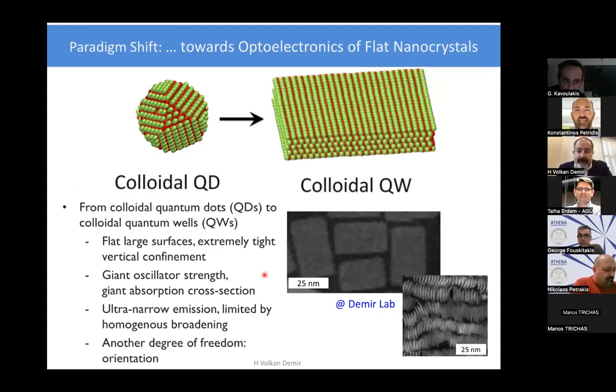And we were quite excited about this facility because now we can make structures laterally large while we keep the vertical confinement the same. Because in quasi-zero-dimensional structure, while we need larger particles to increase, for example, geometrical cross-section, thus absorption cross-section, we had to actually trade off with the quantum confinement. This is just a very simple geometrical argument. In the case of such quasi two-dimensional structures, we don't have to actually trade off with the confinement. We keep it the same, but make each particle geometrically larger.